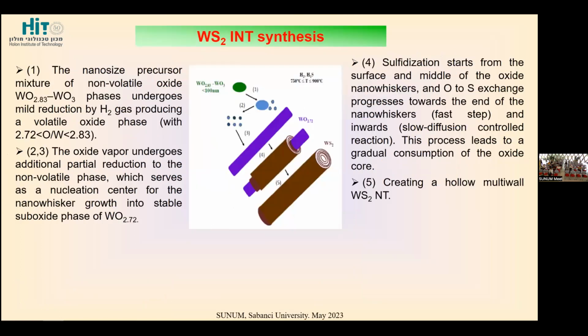In the case of nanotubes, the chemical part is very similar. Again, we start with oxide, but technologically it's very different, though it's made in the same reactor. We first produce the nanowires or nanorods of the oxide, and then starting from this nanorod, layer by layer of WS2 are formed, and we have these multiwall nanotubes with open ends.